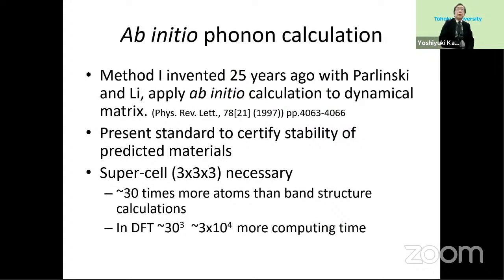everybody uses the phonon calculation, ab initio phonon calculation. I invented this 25 years ago with Parlinski and Li, and everybody uses this formulation to check the stability of the system. So based on density functional theory, we can set up atomic structures, but we should confirm those atomic structures are stable, and by applying the phonon calculation, there should be no soft phonon. If there is, the structure is broken, not stable. So if there are no soft phonons, for the atomic structures predicted by density functional theory, we can say this should exist. So this is the basic idea up to this level.